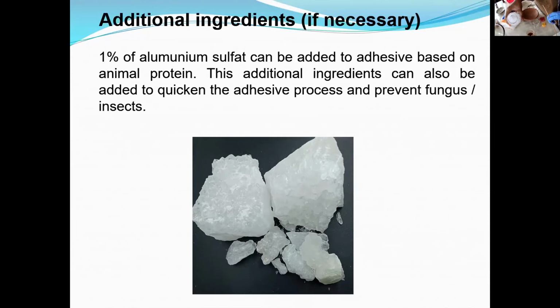This is called tawas. Usually this is used to help clean water. We just use 1% of this material, aluminum sulfate, and dilute it with water that will be used to create an adhesive solution when it's mixed with gelatin. You can use this or not use this, depending on your necessity.